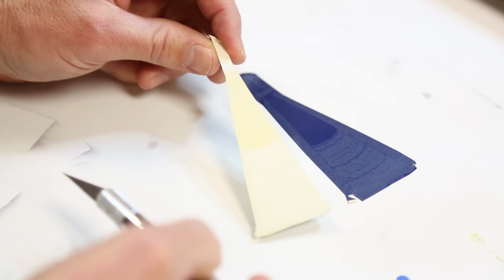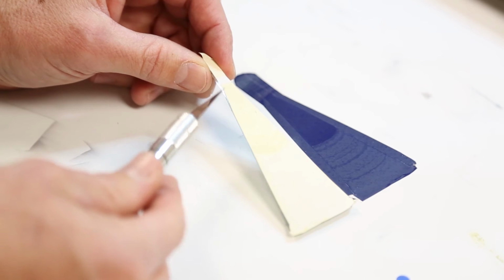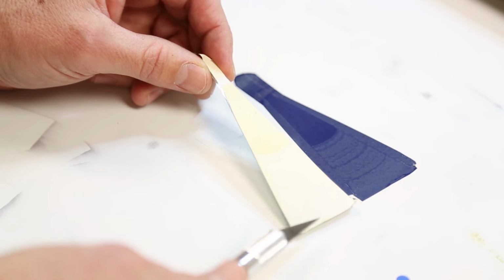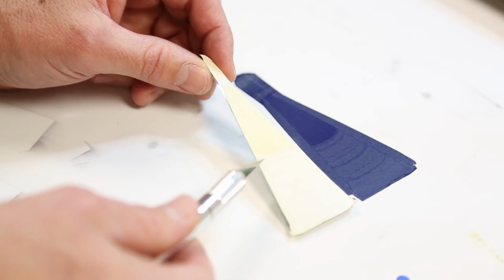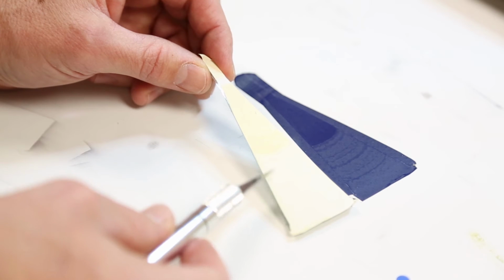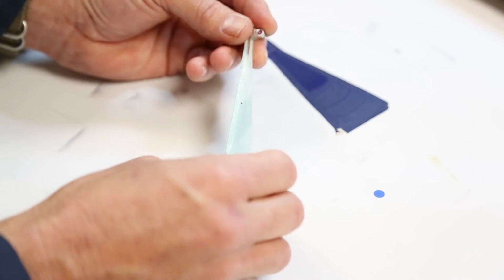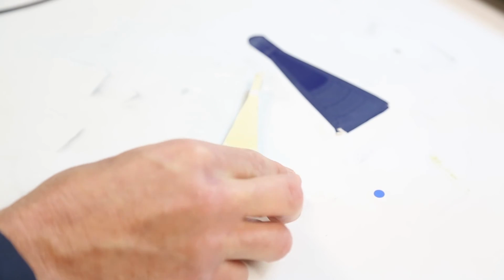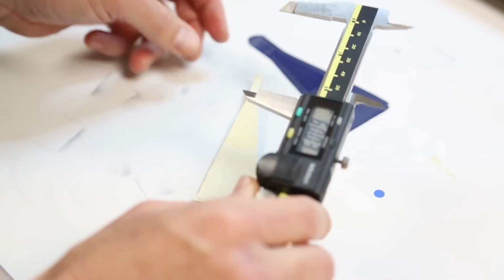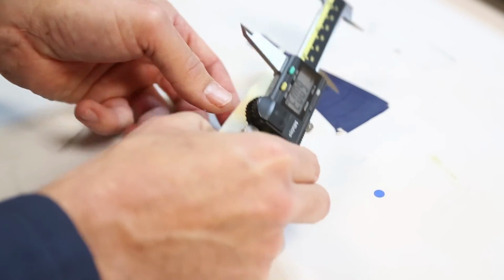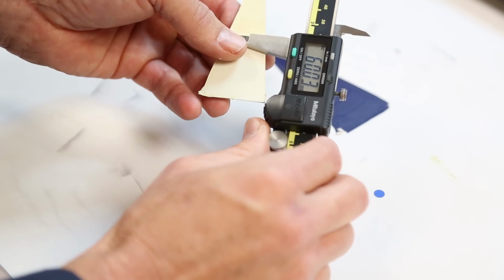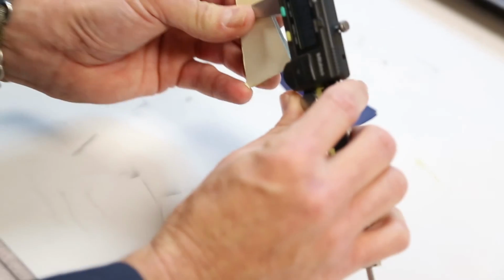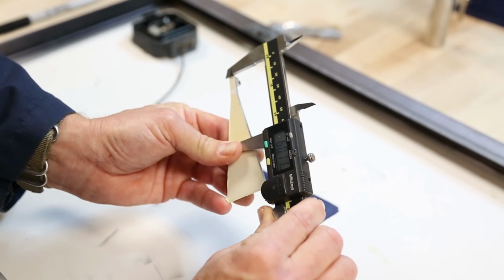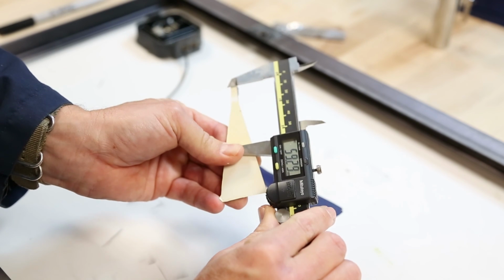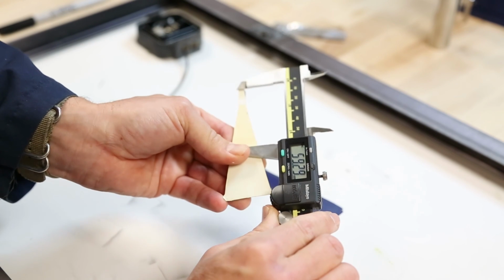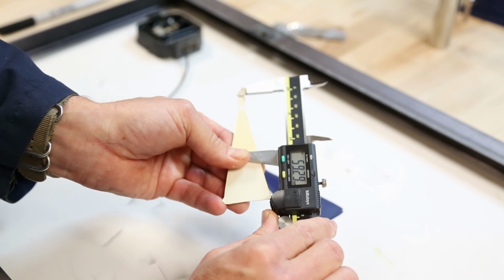Also on the beam, it might be harder to see. The shade of yellow changes from a darker yellow to a lighter yellow from where the measurement ended and where I physically pulled the beam off. To measure the final D-bond length, I always like to use a nice pair of digital calipers, and again, I measure from where the D-bond finally stopped to the center of the loading tab. And for this sample, I'm measuring about 59.3 millimeters.